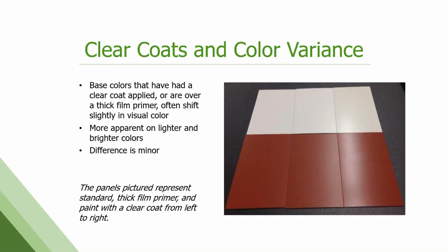The pictures there represent standard on the left. The middle is with the high build primer, which really doesn't affect color much, and then with the clear coat on the right. And you can see that the white samples at the top has shifted yellow a little bit. The yellowness of the clear comes from the semi-transparent UV blockers that they have to use in that coating, so it has long-term performance. If it was truly clear, it wouldn't hold up outside and would delaminate.